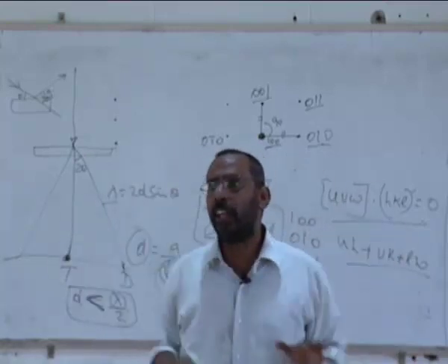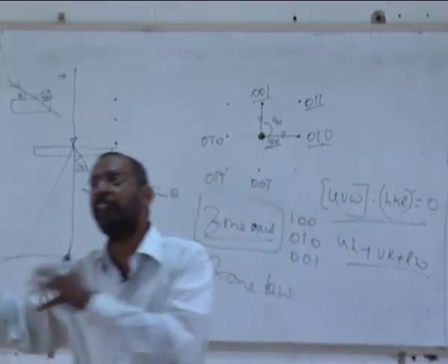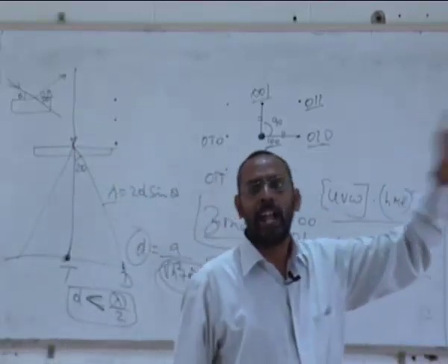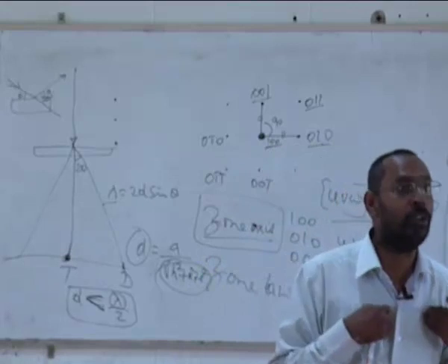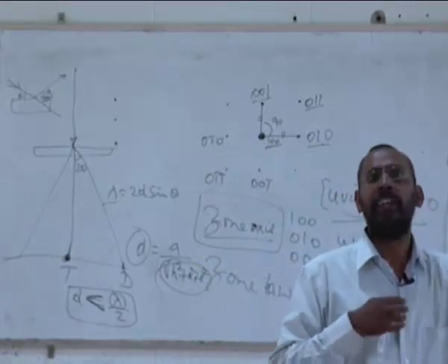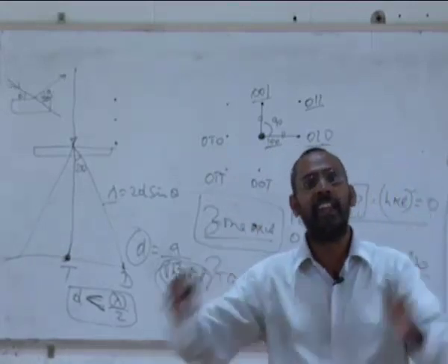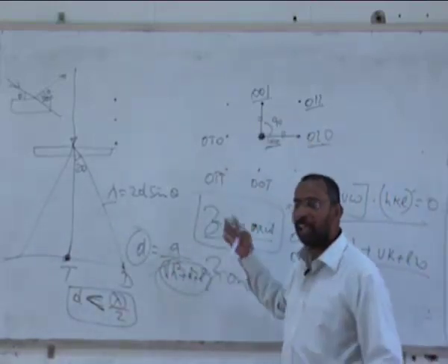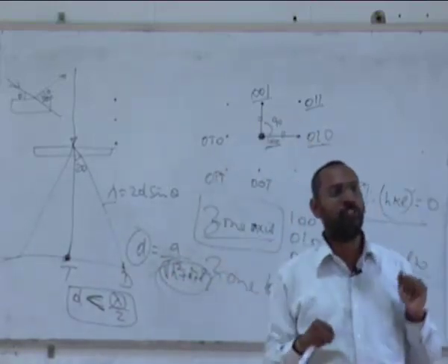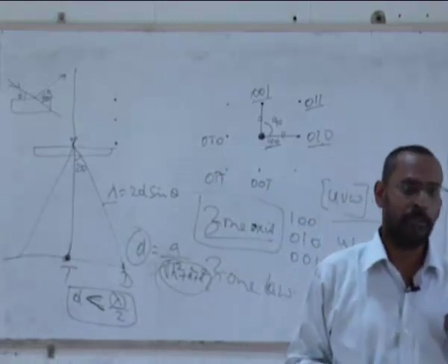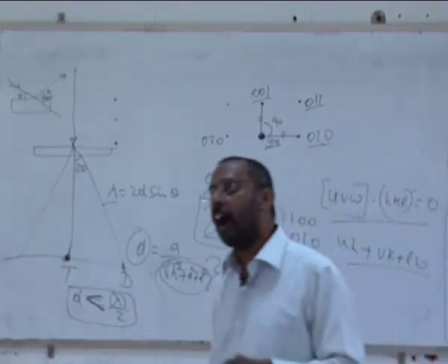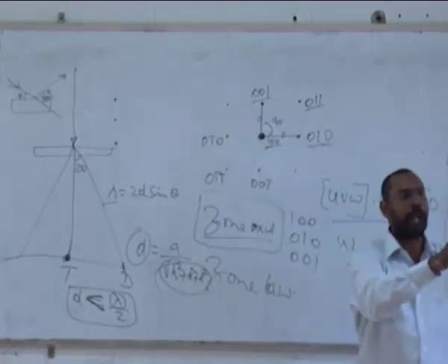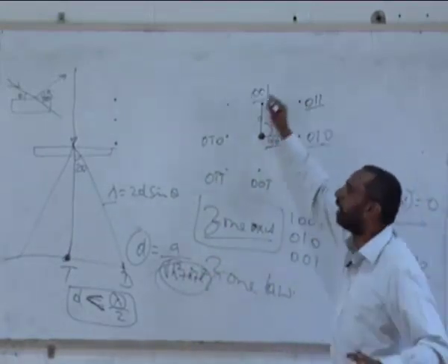Now, these are expected phases, so I can generate diffraction patterns from each of these phases by giving the lattice parameters of those phases. If I know those lattice parameters and the crystal structure of those phases, I can generate diffraction patterns. And I get a diffraction pattern like this. I compare this diffraction pattern with those generated diffraction patterns, and the moment this pattern matches with one of the generated patterns, immediately I know what the HKLs are.